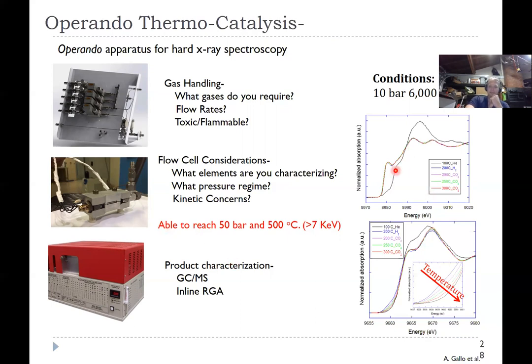And you can see an example of these experiments. These look like zinc edge, is that right? No, this is copper up top and zinc at bottom as a function of temperature. And what happens under different environments, you can see 200 C under hydrogen, CO2. So you can monitor the state of your system with reaction parameters.